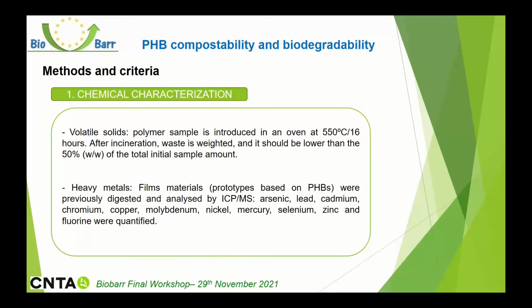Methods and criteria. Regarding the first essay, chemical characterization, assays pretend to study the toxicity of the tested materials. There are 2 methods. Volatile solids, where the polymer sample is introduced in an oven at 550 degrees for 16 hours, and after incineration, waste is weighed, and it should be lower than 50% of the total initial sample amount.